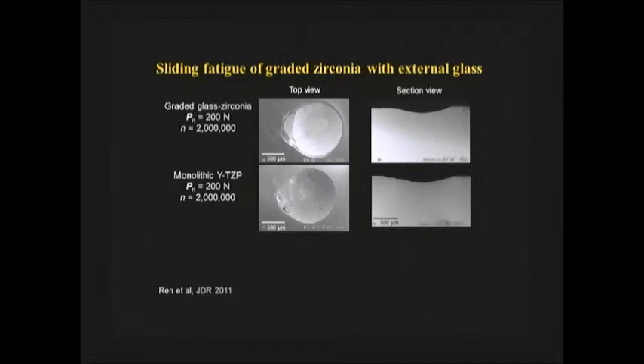And this is the top view, what we see, the contact area with a little nose in the front. And the side view shows a very smooth crater here. You compare to zirconia, very similar. If you zoom in, what we see is the contact area from the residual glass to the graded structure to the monolithic zirconia core is a smooth transition. There are no cracks there, so there wouldn't be any potential chipping or anything formed.